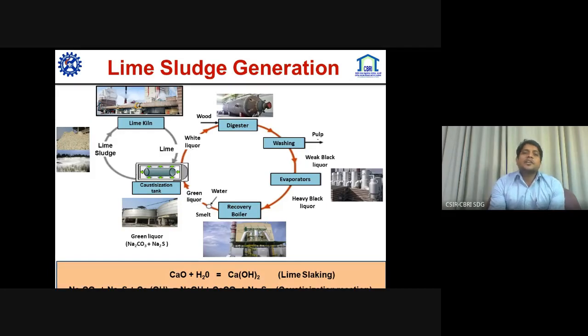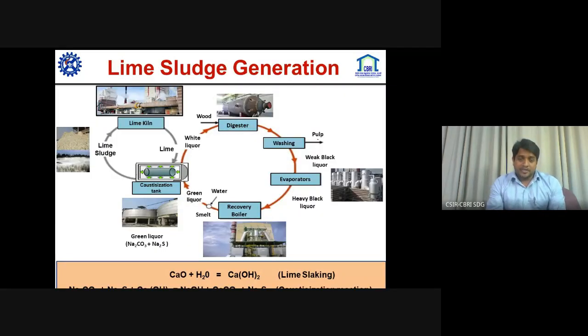So the lime kiln will convert this lime sludge into lime again. I mean, calcium carbonate to calcium oxide. It will require a temperature of 750 to 850 degrees C, and lime sludge will be converted to lime. So they can reutilize lime sludge in the paper industry as lime. So nothing is going out with this process.